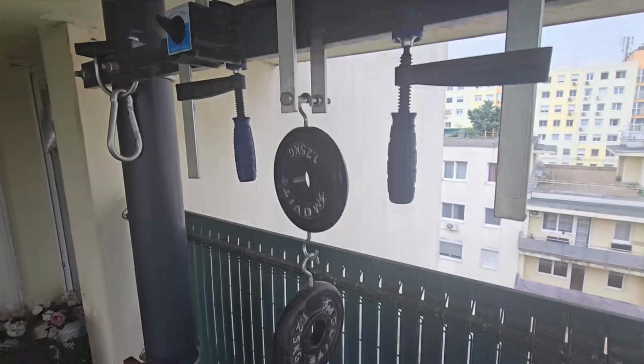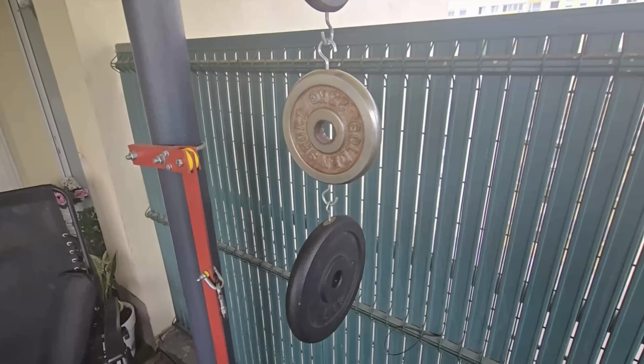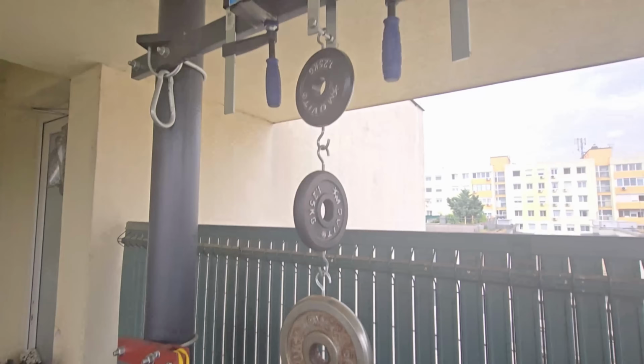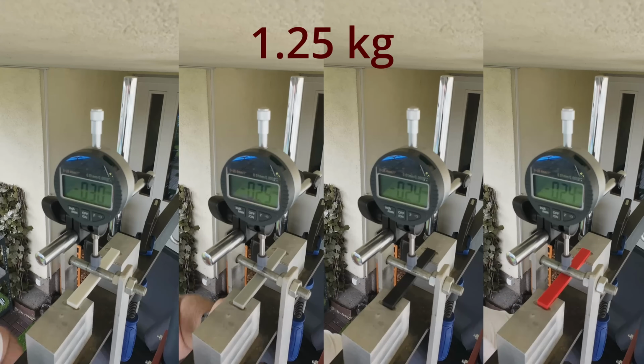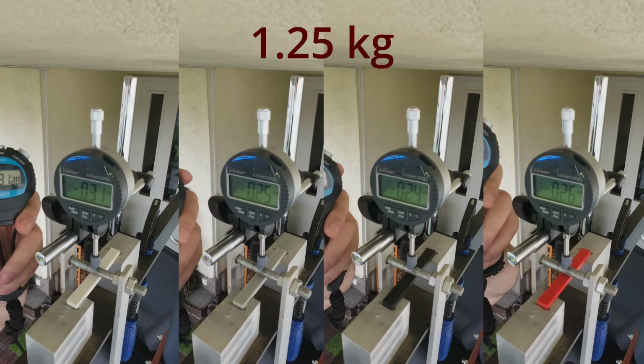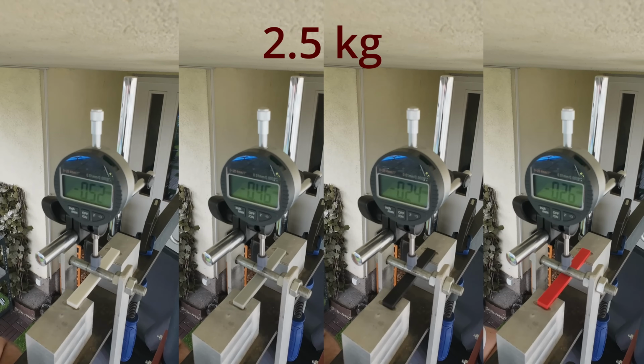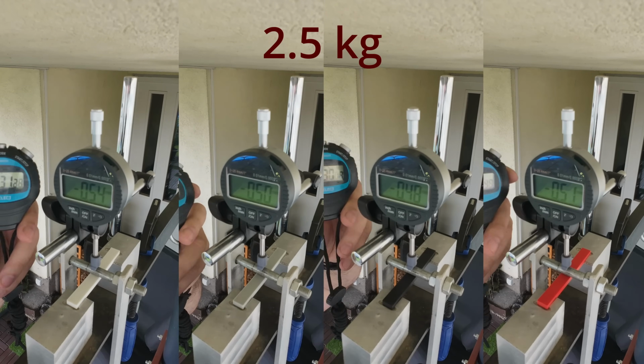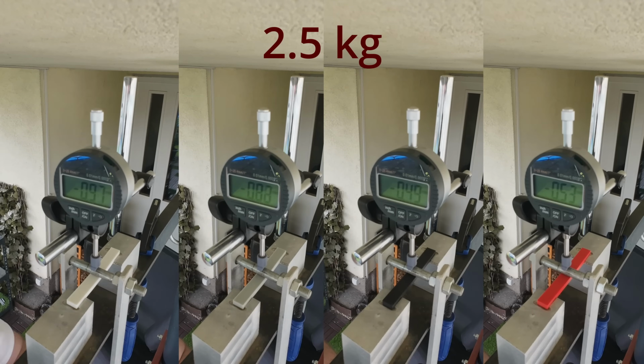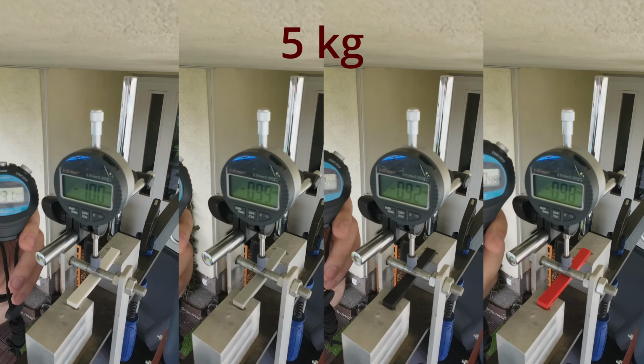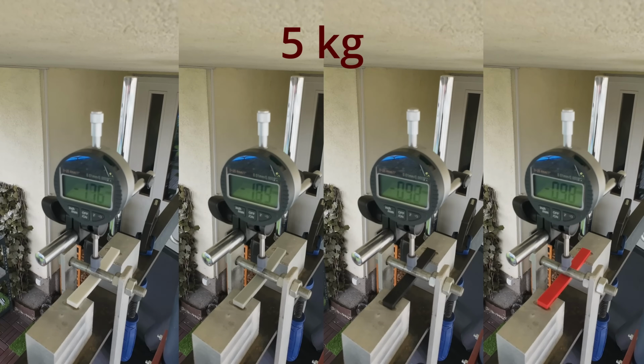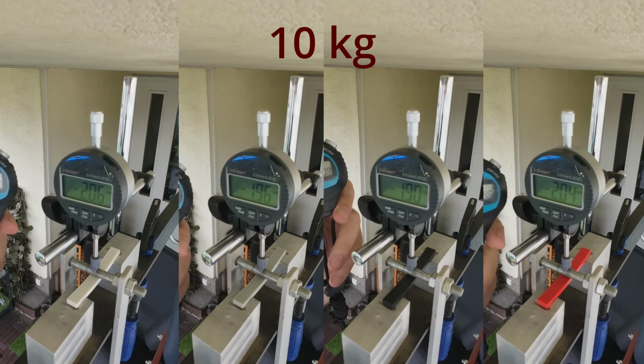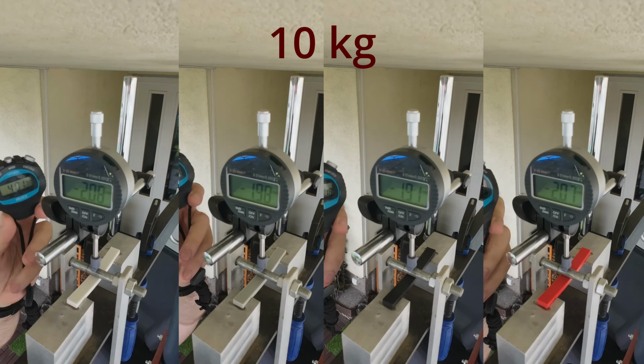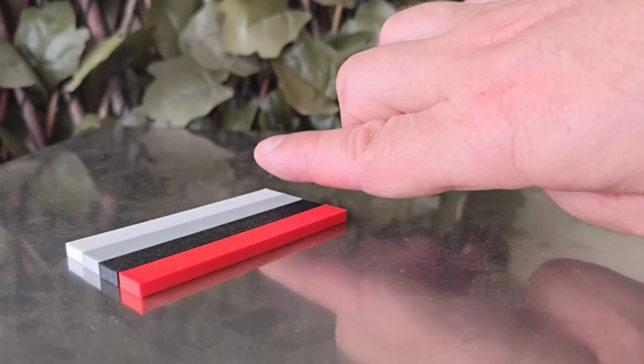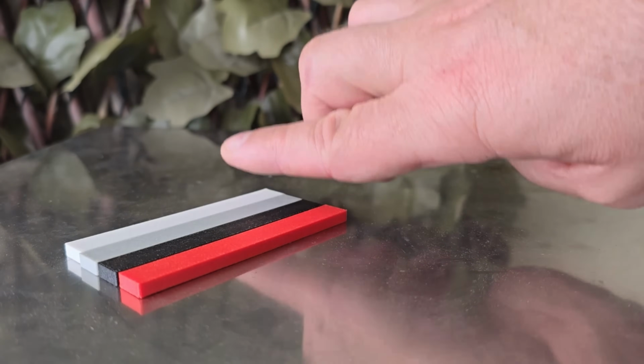3-point bending test. Here you can see my setup where all loads are placed, but I will place them one by one and I will measure the deformation after 1, 30 and 60 seconds. Here you can see side by side all four colors. This is a sped up video, currently under 5 kg load, 10 kg. And after this test, I can see very minimal permanent deformation, hardly noticeable.